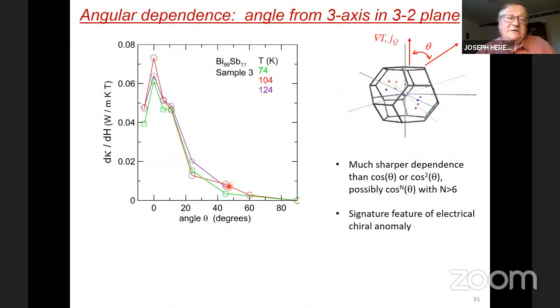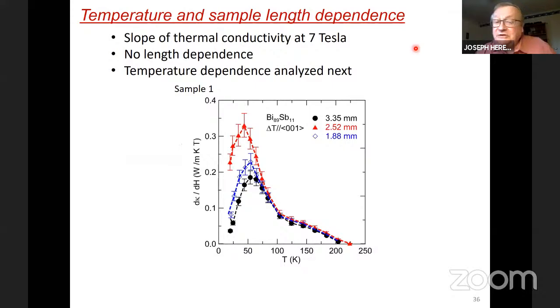Angular dependence, I show that here, it's quite sharp. It's much sharper than a simple sinusoidal dependence on the angle between the magnetic field and the current flow, the heat flow. It's something like a cosine to the power n, maybe 6 or some such number. Now, let me then show you here temperature dependence and length dependence. These are samples of different lengths and the temperature dependence thereof. So this is simply the slope, dK/dH at 7 Tesla. You see that the temperature dependence is pretty much the same. There is no monotonic dependence on length. This is just sample to sample reproducibility.